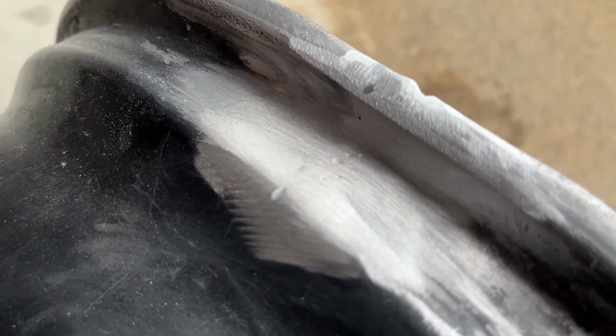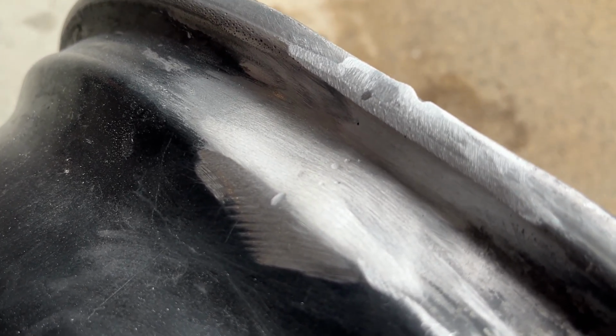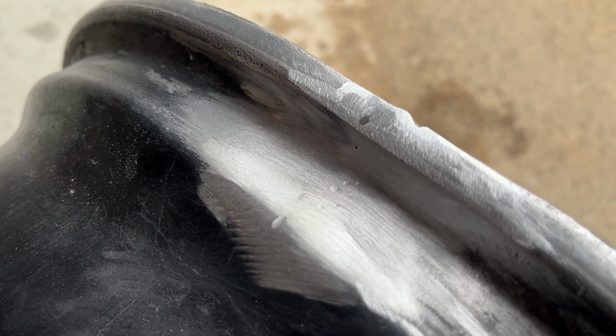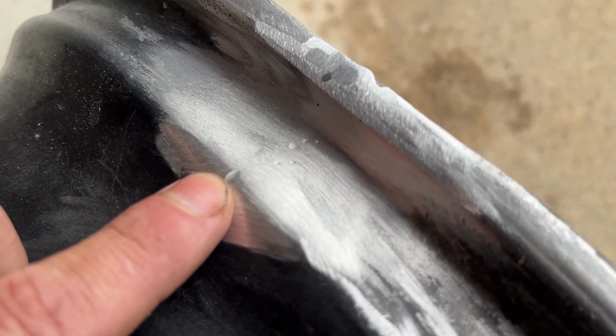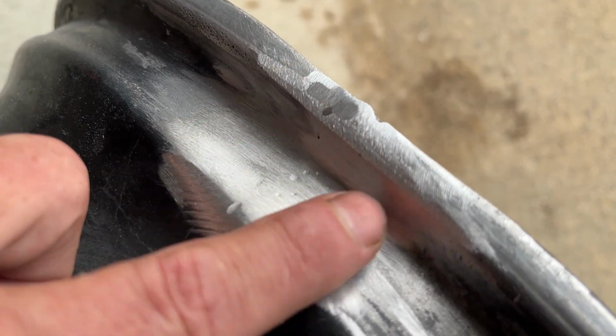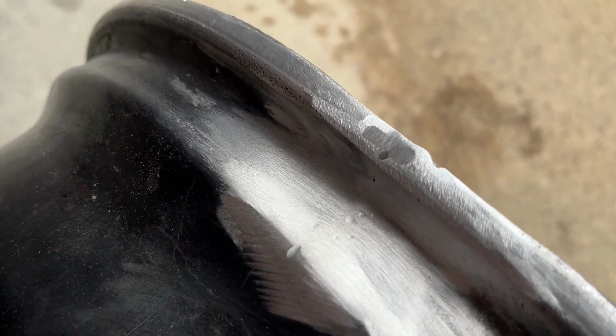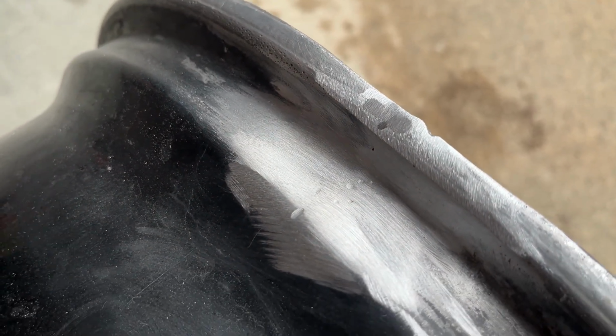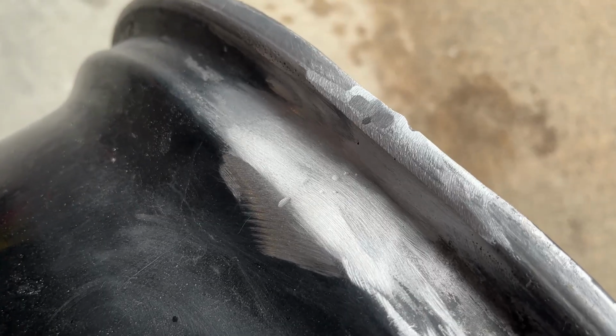I saw no evidence of cracks on the inside or the out. And as you can see, we're at room temperature. Aluminum does solidification cracking or hot cracking. So chances are, if the crack's not showing up right now, it wasn't caused by welding this time. So we're going to end up putting a nice cover pass on here that we can blend back down, and hopefully we won't continue to see those pores. The fewer pores, the less likely it's going to leak again.